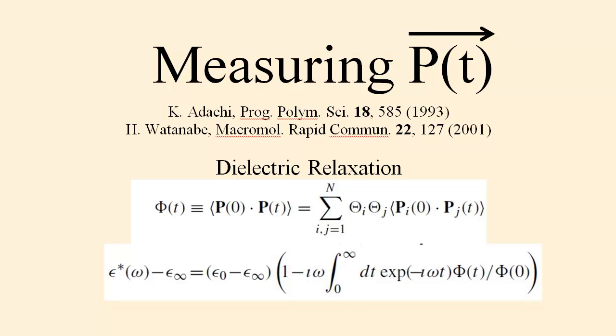Now I said we vary the frequency, and that's because you often do these experiments not in time domain as implied by phi of t, but in frequency domain as implied by the complex dielectric constant, which is a function of frequency and which is related to a time Fourier transform of phi of t. That's what we actually measure.